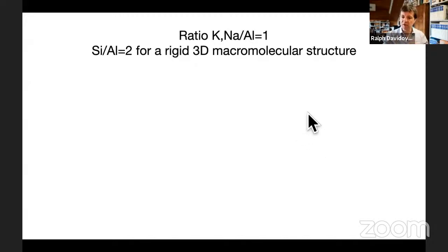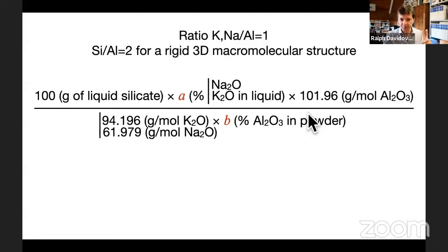This is an example for a ceramic-like geopolymer with only 2 ingredients, silicate and metakaolin. And this is the formula. We start with 100 grams of liquid silicate, multiplying by A, which is the percentage of K2O or Na2O in liquid. This percentage is given by the supplier of your silicate, and multiply it by the molecular weight of Al2O3, divided by the molecular weight of K2O or Na2O, multiplied by B, which is the percentage of Al2O3. Here it is metakaolin. This percentage is given by your supplier.